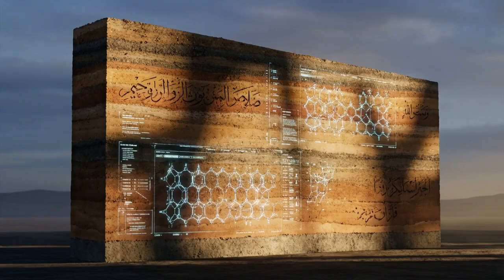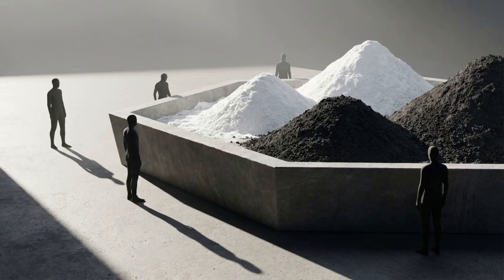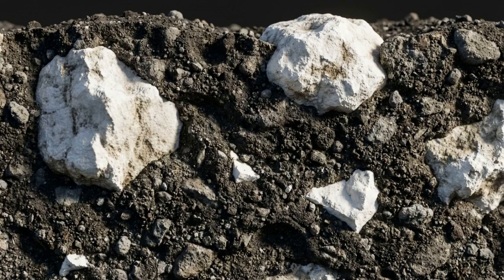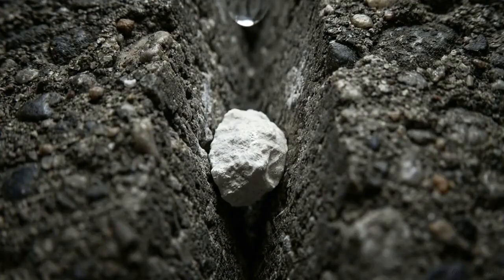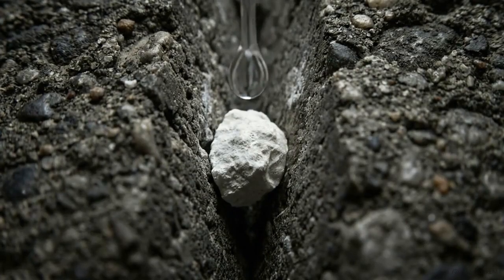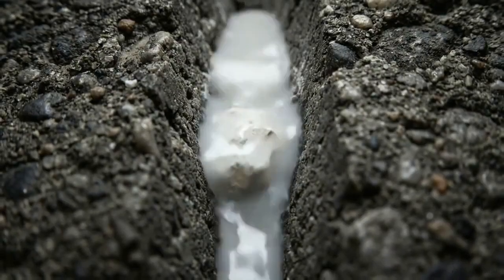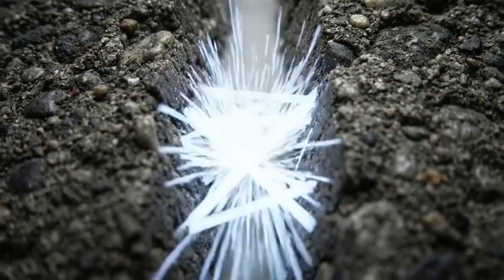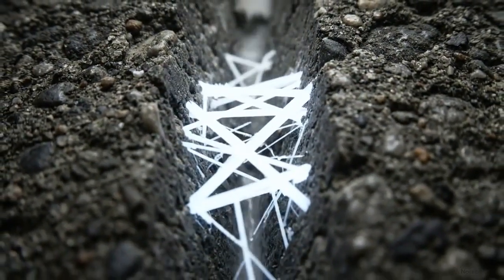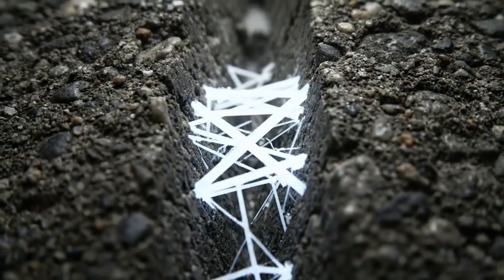Their chemical analysis revealed a process called hot mixing. Contrary to ancient texts, the Romans ground quicklime dry, mixed it with volcanic ash, and added water strictly as the final step. This high-heat reaction trapped brittle lime clasts directly within the concrete matrix. When structural microcracks form, these trapped clasts dissolve upon contact with ambient moisture. The resulting calcium-rich fluid quickly recrystallizes, actively healing the crack.